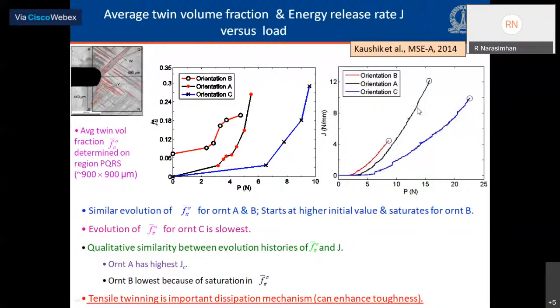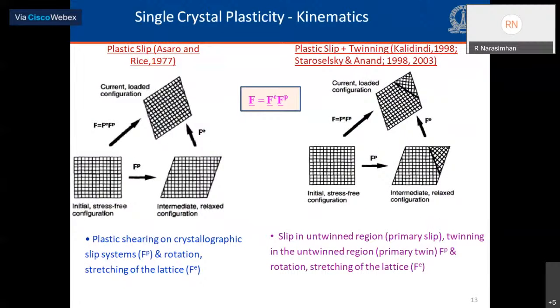The circular symbols indicate the stage at which the specimen failed. The qualitative similarity between the twin area fraction near the notch tip and the energy release rate histories suggests that tensile twinning is an important dissipation mechanism and can therefore enhance the toughness. In order to understand the experimental results more clearly, we also did complementary numerical simulations, finite element simulations, using a crystal plasticity model, single crystal plasticity.